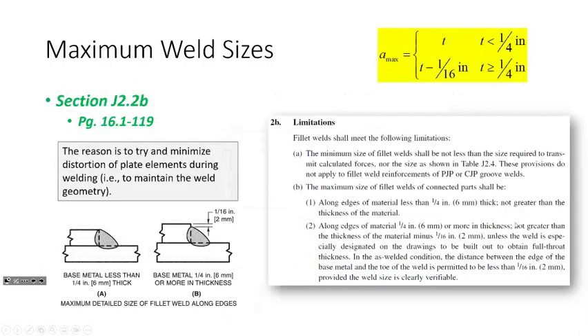The reason for a maximum fillet weld size is so that you don't melt the plate, okay? So imagine if you're trying to weld two 1/2 inch thick plates together. You kind of have to back off the weld a little bit, because if your weld gets big enough to be the thickness of the plate, you will start melting the plate and then you won't have proper weld geometry there where the plate and the weld meet. Does that make sense? So for most structural connections, if we want to determine the maximum weld size, we take the thickness of the plate and we back it off a 1/16 of an inch, and we say that's about the maximum size that your fillet weld could be.